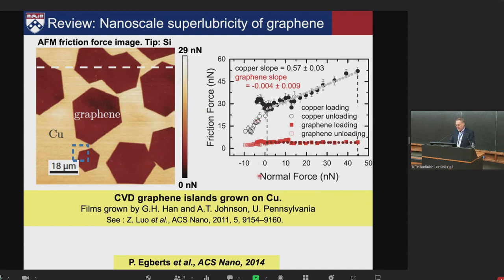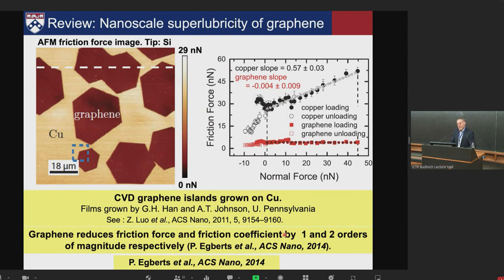So this is the friction force versus normal force for the copper. You can see it's up here and it keeps increasing. Down with the graphene, not only are the forces lower, but there's almost no slope, almost no increase in the friction force with load, which is something that always surprises me because I keep expecting, well, if you push harder, the contact area goes up. Shouldn't you see more friction? But the friction coefficient is almost vanishing, statistically indistinguishable from zero for this material. That's been seen on graphite before by many others, and we also see it on graphene. So right away, that's one example of how you can have a strong effect on friction force and friction coefficient through this single layer of graphene.